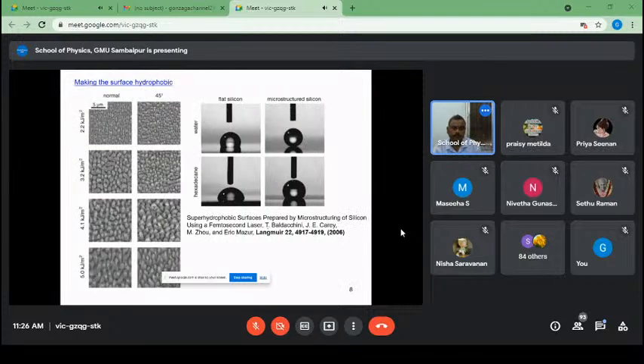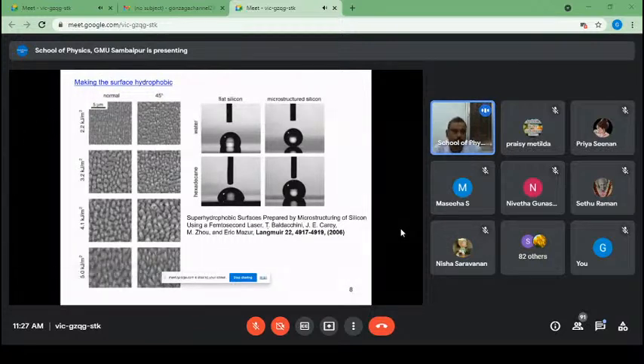You see, this is one application where you can control the hydrophobicity of the surface of any material. For example, in this case, the silicon surface has been processed by the laser, and various structures are generated. In this case, this was done at a fluence level of 2.2 kilojoule per meter square. These structures were periodic.